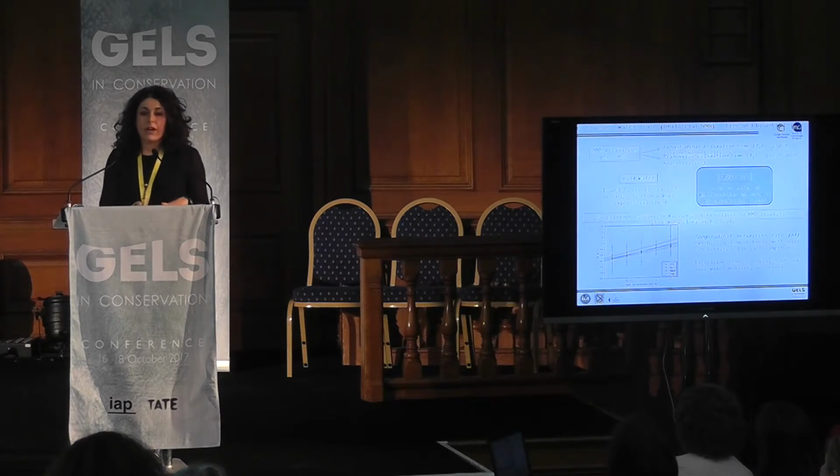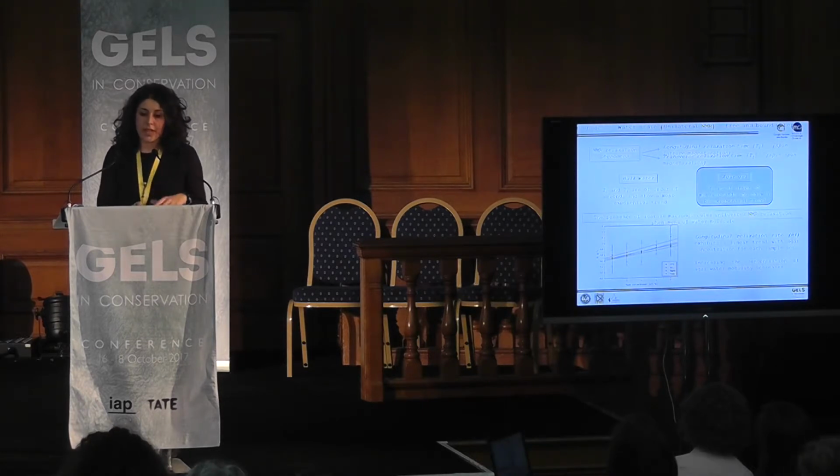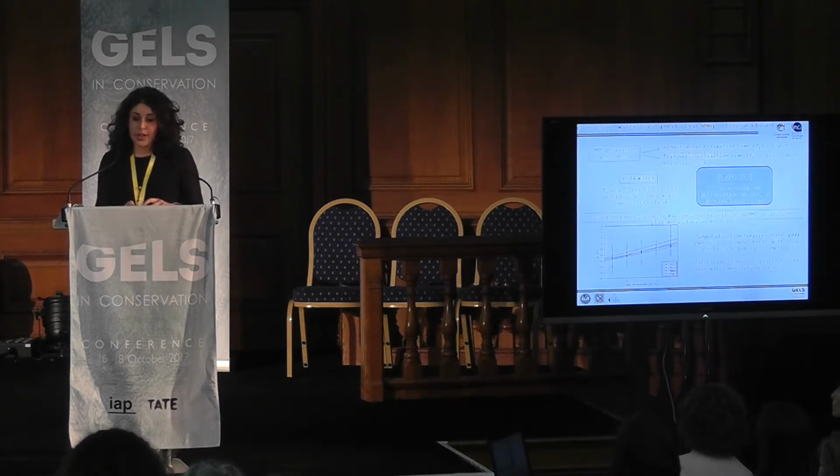If I have a macromolecule like agarose or agar, in this case T2 is of the order of milliseconds and shows an exponential trend. We can say that the presence of agarose influences the transport phenomena and the movement of the free water. This is confirmed by the longitudinal relaxation rate versus the concentration, where we can see a linear tendency with the increase of concentration. So, increasing the concentration, water mobility decreases.